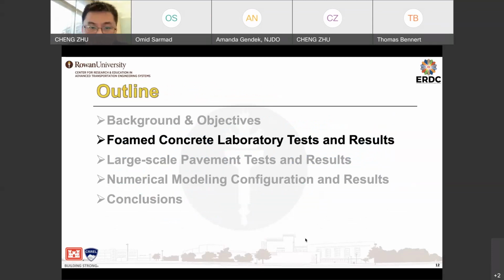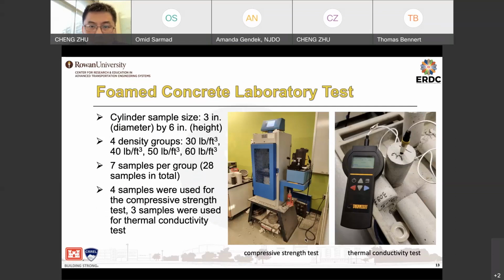Next, I want to show some of the laboratory test results we have. In the lab, we prepared a number of samples with different densities. We tried 4 different density groups, as shown here, and there are 7 samples per group, so in total we have 28 samples. 4 samples per group were used for the compressive strength test, and 3 samples were used for the thermal conductivity test. This is the setup we used for the uniaxial compression test, and that's a thermal conductivity meter used to measure the thermal conductivity of the foam concrete.